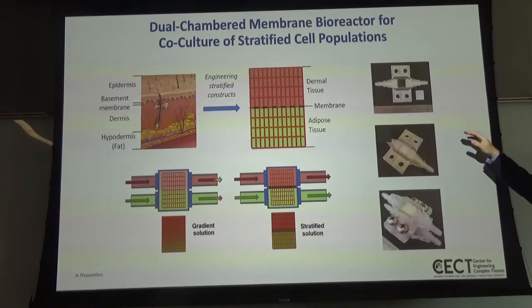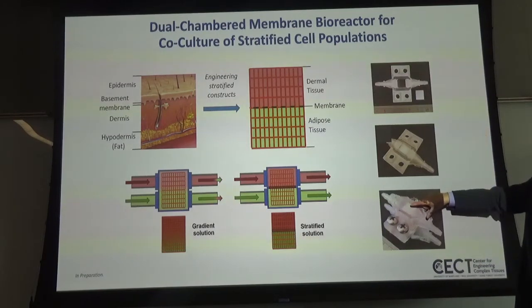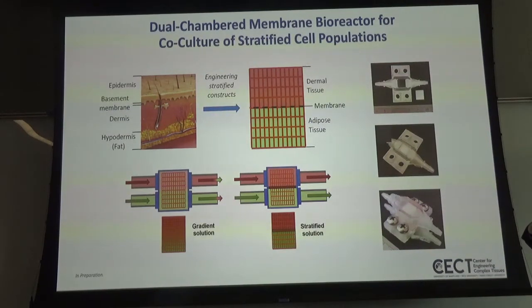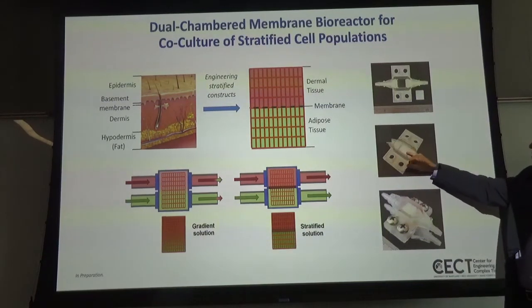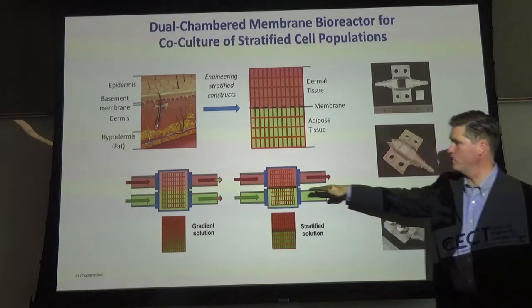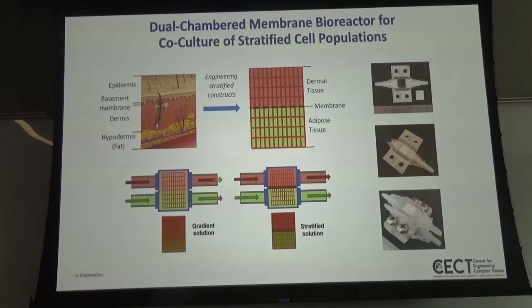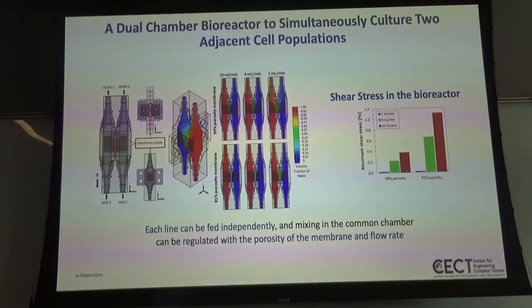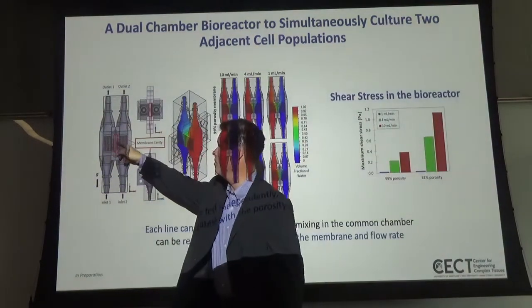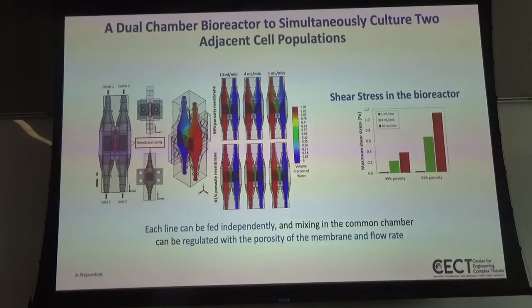So again, using a printing approach, Javier built these bioreactor systems, and you can kind of see it here. It's about yay big. It has two chambers that fit one on top of the other. The scaffold that he was using is just a simple cube-like scaffold with a lattice structure, and then between the two chambers was a separating membrane, and I'll talk about that membrane in a second. So again, we use some CFD approaches to look at flow through the dual chamber bioreactor as well as mixing and the shear environment, establishing that we could indeed flow multiple medias in the two chambers, and the mixing could be regulated by the porosity of this membrane that we inserted between the two scaffolds and the two chambers.